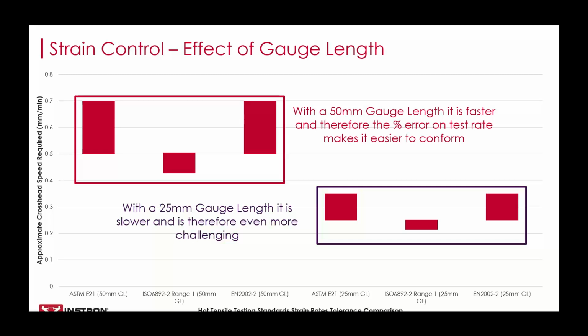So just to summarize here, good strain control is critical for achieving a conforming test to either ASTM E21 or ISO 6892-2. And that control is even more important for specimens of smaller gauge lengths. And although the standards allow for testing in open loop control if closed loop isn't obtainable with your equipment, that presents other challenges, including the increased likelihood that retests will be needed and a slower test overall. Both of these challenges can really get in the way of the efficacy of a test lab.